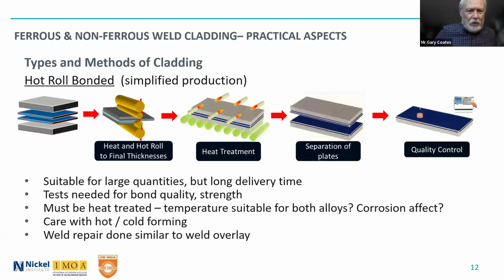And this is a very simplified production scheme. I've left out a few of the steps, but just so you know how it works, on the left there, you make a sandwich. So you have a backing material, a CRA layer, another CRA layer. These are all plates or sheets, and then more backing material. You actually weld it up, suck out any air that might be there, and then at a conventional rolling mill, you heat the slab up and then roll it to the final thickness. You do a heat treatment, and then you eventually separate the two plates. You have a separating compound in between that doesn't allow the materials to fuse together, and then you have your quality control step.